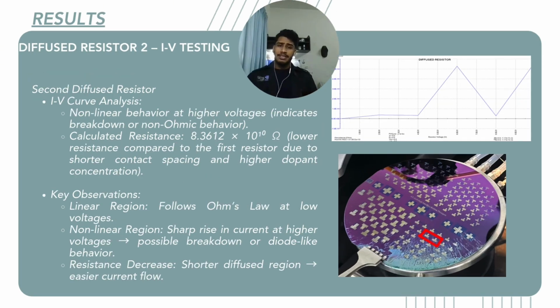Now, the IV for this resistor looks a bit messed up at higher voltages. It showed signs of a linear relationship at low voltages, but as voltage increases, there's a sharp rise in current, and it gets worse as the voltage grows bigger. So possibly it's breaking down at higher voltages. The good thing is this resistor's contacts were closer, so the resistance should be lower than that of the first resistor. And yes, it is, with a value of 8 times 10 to the power of 10 ohm.